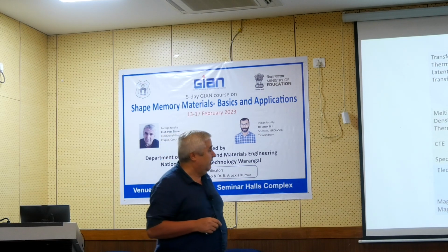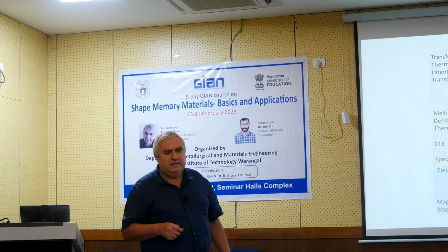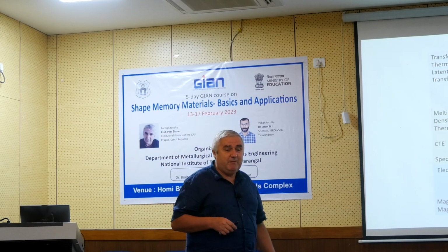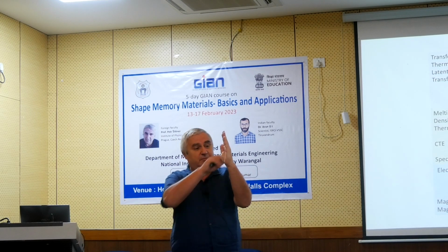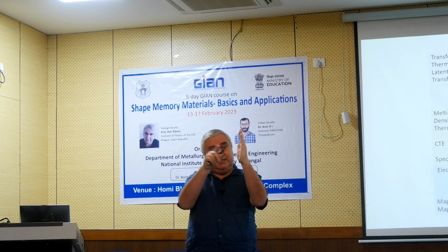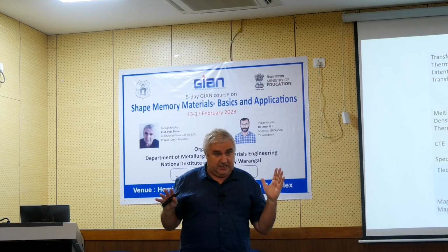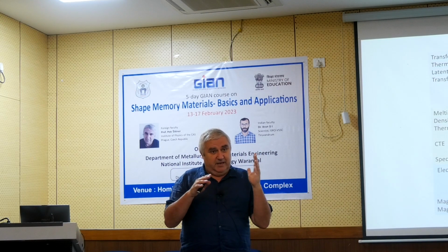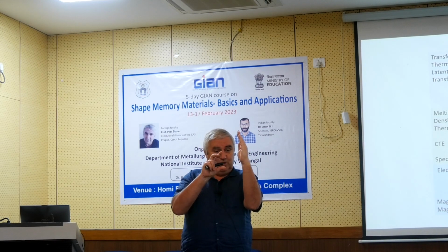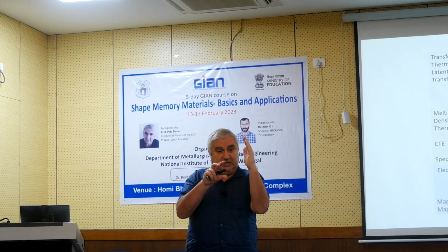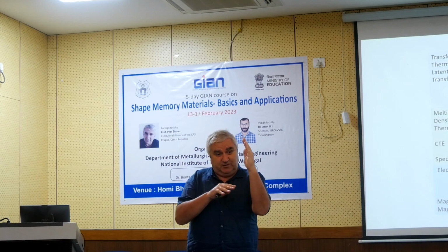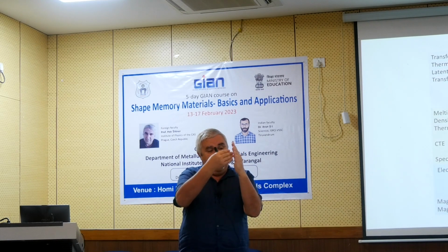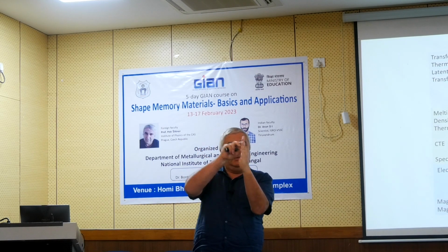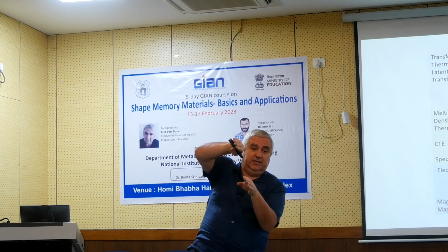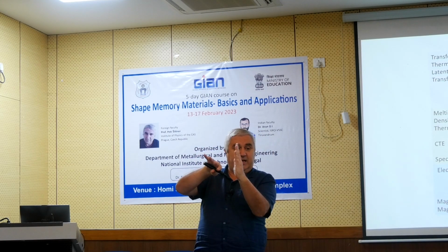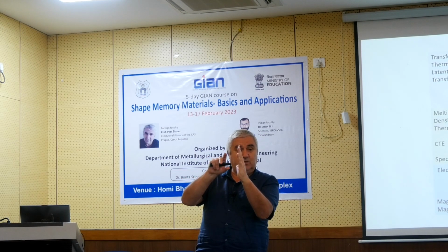It's so simple. So what is the strain compatibility? What does that mean? Well, yesterday I said that between austenite and martensite must be twinned. So if you do it without stress, the material in NiTinol always has to go through the transformation through this twinning, which is a little complicated process, because there are millions of twin interfaces. They have to be added to the material, and then at the habit plane, the strain and shear is the same here and here. And the material does it by creating the laminate. This is the compatibility condition.